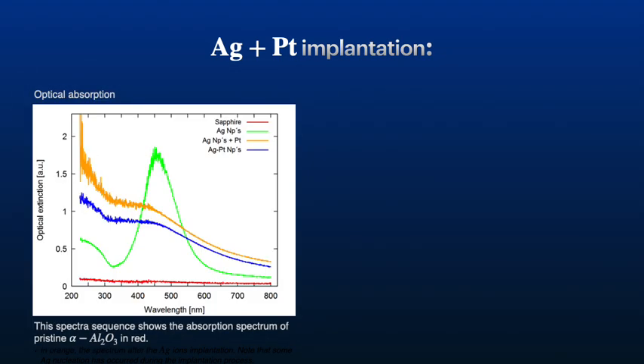We chose this sequence for this set of samples to inhibit the formation of nucleation seeds so that it would take place simultaneously for both kinds of ions. The optical absorption spectrum of this example at the end shows no significant surface plasmon resonance, but only a broadband corresponding to a few remnant silver nanoclusters.